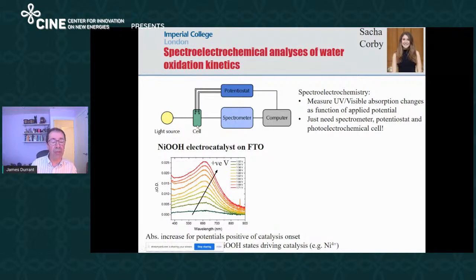If you put your sample in a spectral electrochemical cell, then you can measure the spectrum of the sample. And this can just be a UV-vis spectrometer and a potentiostat, and you apply a positive potential. What you observe for this nickel oxyhydroxide is as you apply a more positive potential, you see the appearance of an absorption band at around 600 nanometers. And this is the oxidation of nickel states to nickel, most likely nickel 4, and this potential range is the potential range of where water oxidation turns on in this material. And so we can use this as a measure of the density of these states.